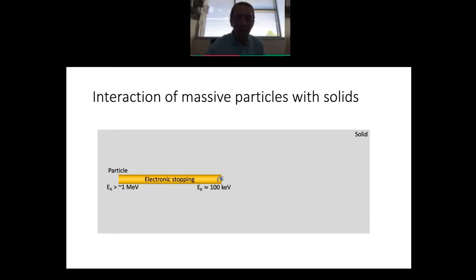So this particle right here is the particle that was flying through the material. It's going to bounce off of a nucleus, right? And when it bounces off, the particle flies off in this direction, and then the nucleus that it bounced off of gets some energy and flies off in a different direction. That's now known as the primary knock-on atom, or PKA. That PKA can bounce off of other atoms, right? So you get this whole cascade of collisions between the impinging particle and various knock-on particles, so primary, secondary, tertiary knock-on particles. This is called the collision cascade.